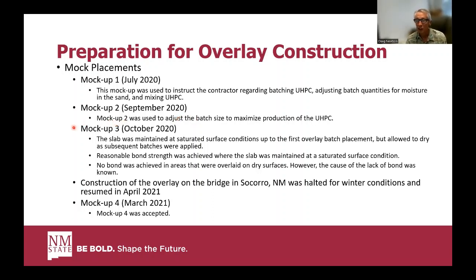Again, an educational opportunity for the contractor, but they didn't want NMSU to just come and work with them by themselves. They wanted to try the mock placement, hoping to pass every time it came up. So, third mock placement. This time, everything actually went pretty well to start. The slab was maintained at saturated conditions. They batched the UHPC in a manner that was perfectly acceptable.